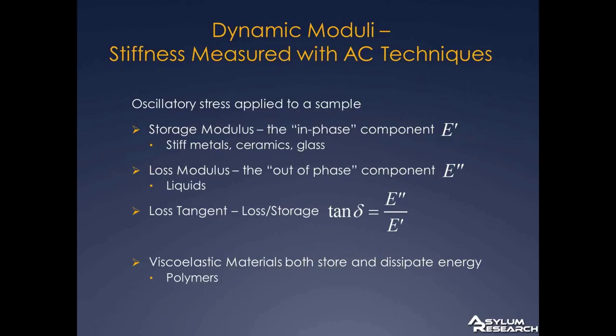Examples of materials with large storage moduli include stiff metals, ceramics, glasses, and so on, things that you think of as elastic. Examples of materials with large loss moduli would be liquids like water. Most of the energy that you put into it is dissipated as heat or other kinds of lost energy. The loss tangent is defined as the ratio of those two quantities. In general, most materials are neither perfectly elastic nor perfectly viscous; they dissipate some energy and store some energy. Viscoelastic materials both dissipate and store it, and examples of those include most polymers.